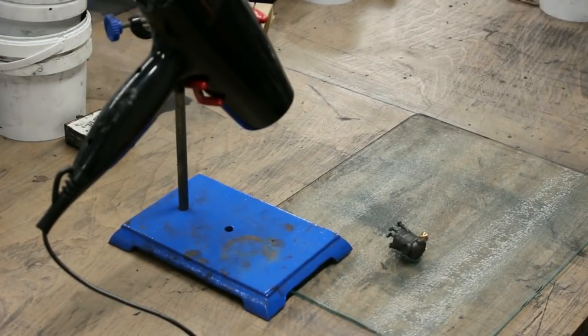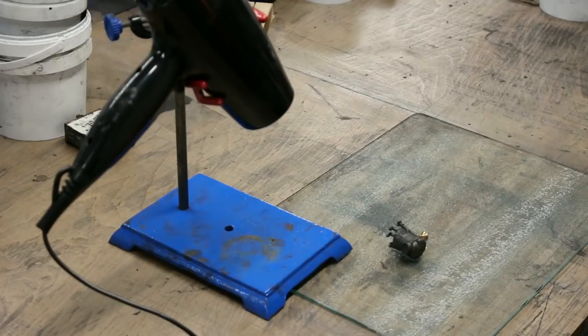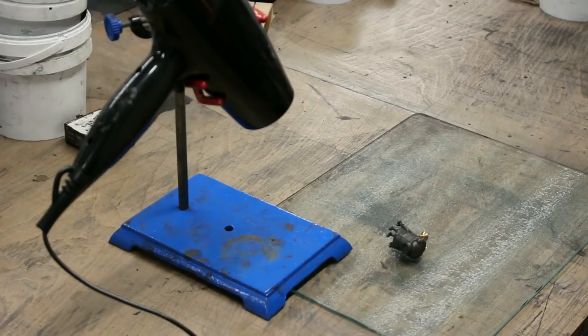And as we've got plenty of little Minions running around here I've grabbed another one earlier and this one here has had three coats on it. You won't need any more than three coats with our water resistant conductive ink. And you can either leave it to dry naturally for an hour or so or you can use a hair dryer on a cool setting for 5 to 10 minutes.